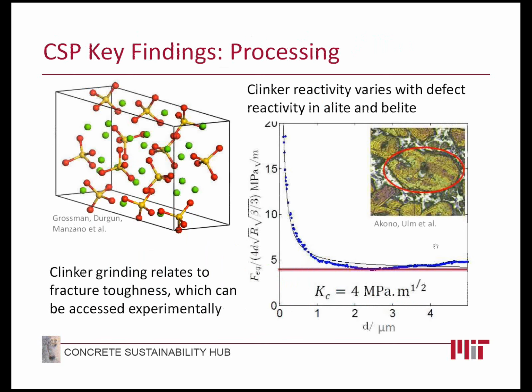On the CSP side, so our concrete science platform side, there are several key findings. I just wanted to highlight a couple that I think are most intuitive. So starting with the very beginning of creating cement, paste, and concrete, we've thought quite a bit about clinker reactivity. For example, those of you who work on this side of the house know that there's a gross difference in the reactivity and the dissolution and the precipitation and the kinetics of forming cement paste using clinker that is rich in alite versus belite. And these are different crystal structures.